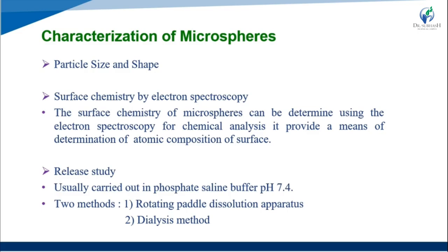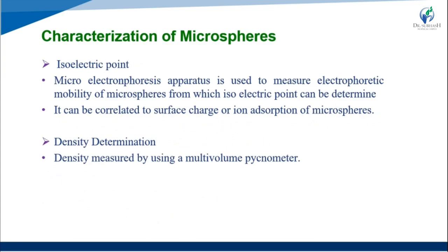Now, drug release study, usually carried out in phosphate buffered saline at pH 7.4, with two methods: the rotating paddle dissolution apparatus and the dialysis method. Now, isoelectric point. A microelectrophoresis apparatus is used to measure the electrophoretic mobility of the microsphere, from which the isoelectric point can be determined and correlated to surface charge and ion adsorption.